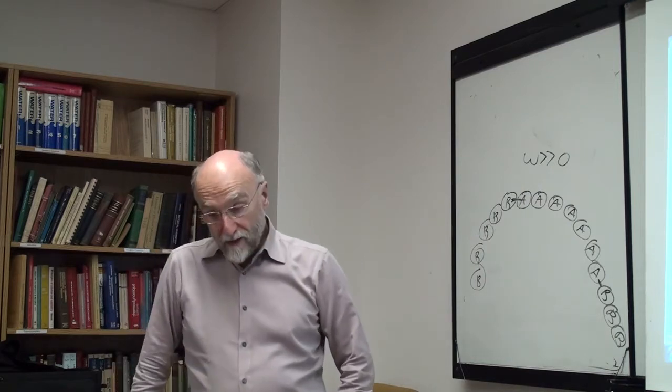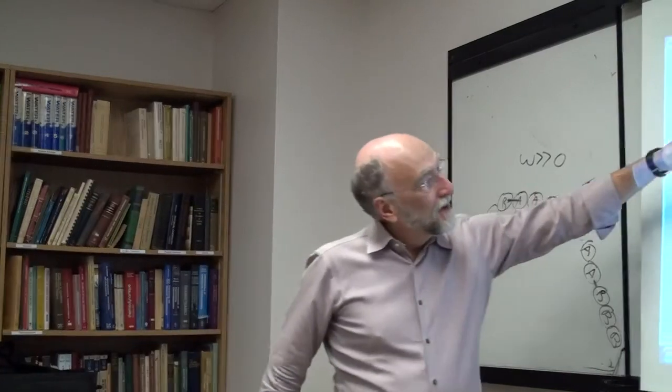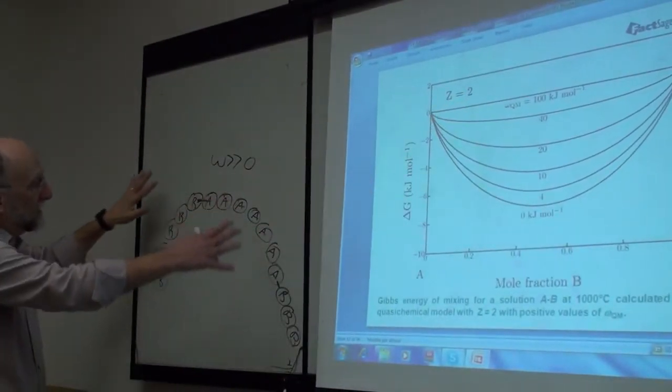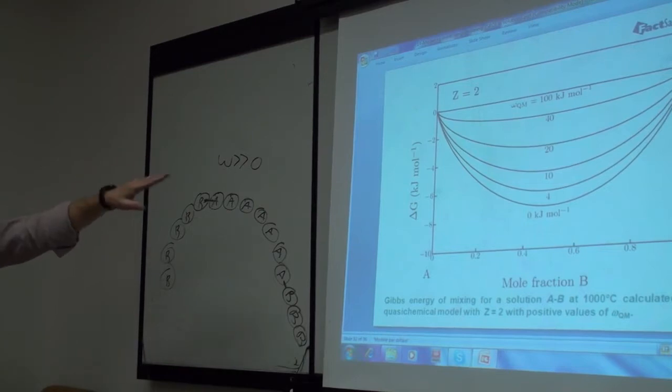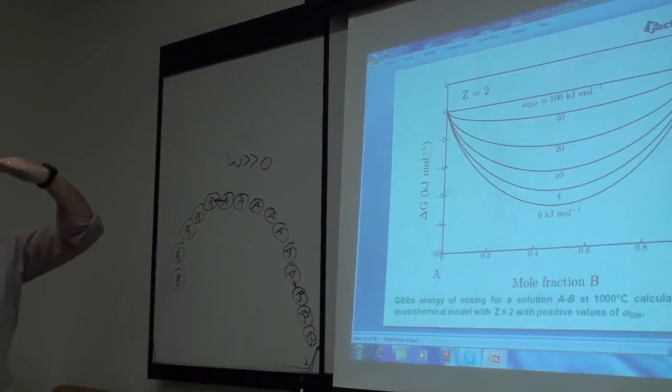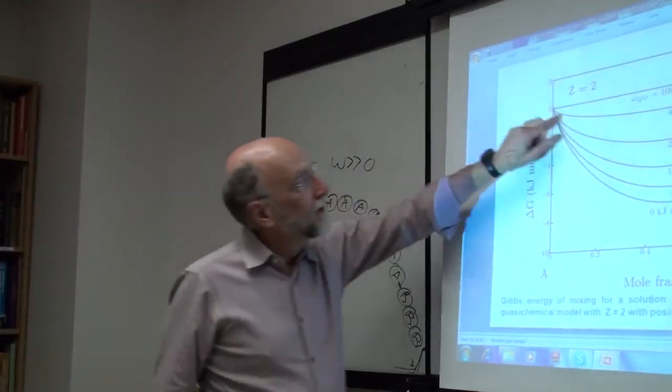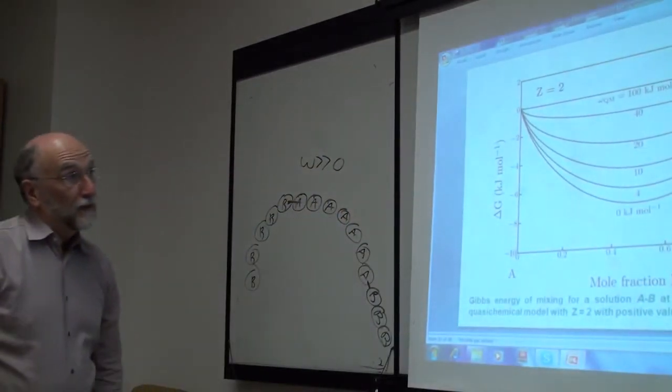Whereas if you have a Bragg-Williams model, even in a one-dimensional model, what's happening basically is you're decreasing the number of AB bonds smoothly, and eventually, as omega becomes very large, the number of AB bonds just smoothly goes down to 0, and you never get a bump in the middle. It's always better to have a little bit of entropy in the middle that comes down that way.